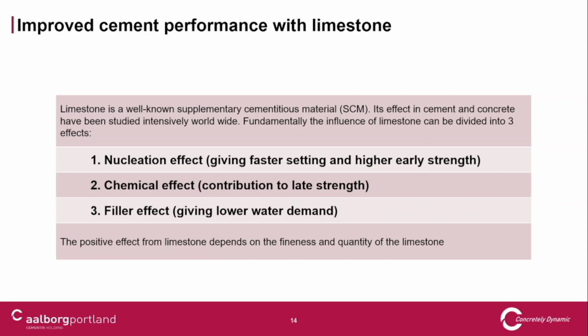We see that limestone actually has three different effects on cement performance. There's a nucleation effect, where the limestone helps in the beginning to form cement reaction products. There's also a chemical effect, where there's actually reaction between limestone and cement minerals, forming new materials. So it's not pozzolanic, but there is a chemical reaction which helps, and there's also a filler effect.